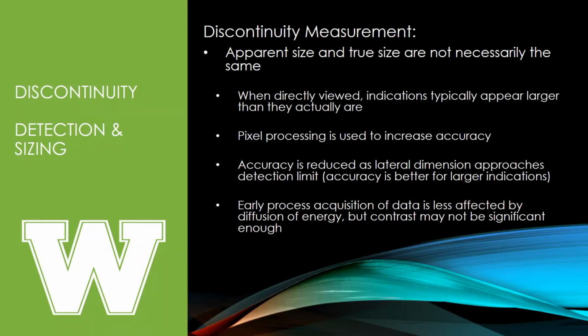And that comes into play. That's really important when you're doing a quantitative analysis and there's a maximum damage limit, for instance. You want to be careful about whether it's exceeding that limit. So to increase that accuracy, oftentimes pixel processing is done, where a computer algorithm looks at those temperatures pixel by pixel and, based on the behavior, compares pixels next to each other and surrounding each other. There are algorithms out there that can really nail down where the damage is and where it's just the heat diffusing into the surrounding area.